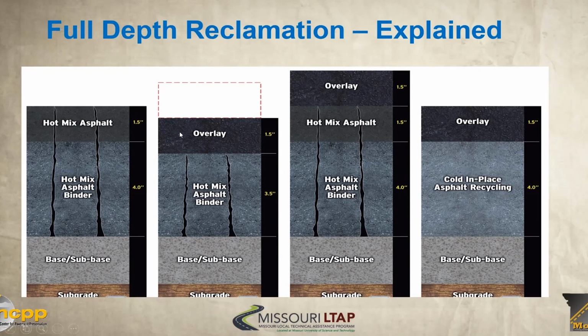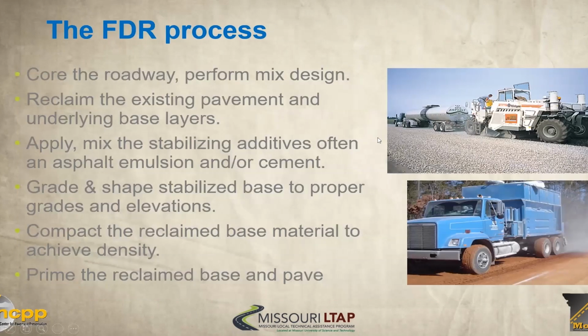But here's another reason we don't want to just mill and overlay. So if we did a 1.5 inch mill and overlay, the cracks are going to come back up through, and then we're going to have to overlay it again. And what we're building here is a perpetual crack. And so this is why we don't want to go in and just willy-nilly mill and resurface. So what do we do? We want to core the roadway. We want to look for any base deficiencies, or in this picture, you can see a sand clay base, which would indicate we need to do something to stabilize that base. And this is a contributing factor of why the asphalt looked terrible on the surface.